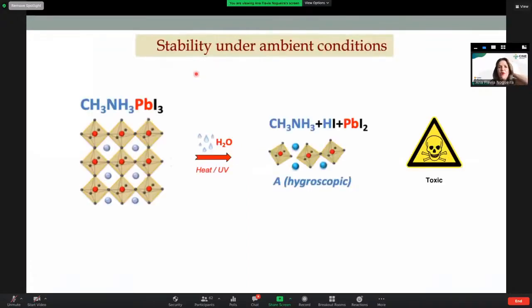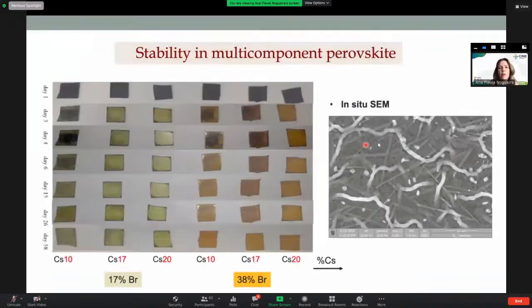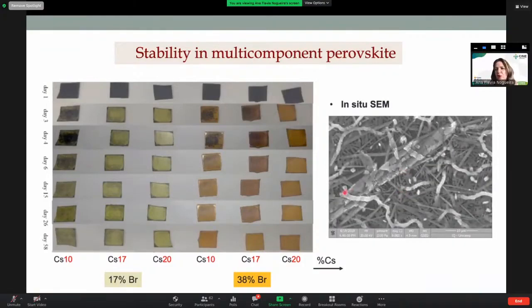just to show what the problem with the perovskites is, as I mentioned, it is the degradation, because in the case of MAPI, if you have moisture or heat, you end up with lead iodide, which is very toxic, okay? Another point, you can see this is the evolution. We did some in situ measurements on perovskite films under moisture, we increased the moisture inside of our microscope. You see here the degradation and the evolution of this kind of microrods.